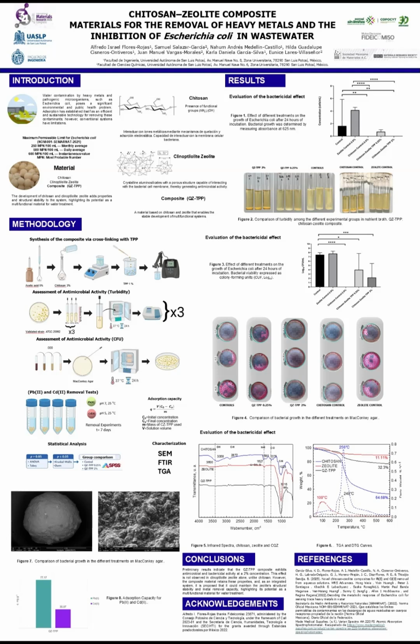The structural stability of the composite is closely related to cross-linking with sodium tripolyphosphate, since the formation of ionic bonds between the amino groups of chitosan and the phosphate groups of the cross-linking agent creates a more stable structure in an aqueous medium, reducing the polymer's solubility without compromising its antimicrobial activity. The preservation of activity observed for the 2% QZ-TPP composite supports this behavior. Several studies have shown that ionic gelation with TPP improves the physicochemical stability of chitosan-based materials and allows them to retain their bactericidal capacity.